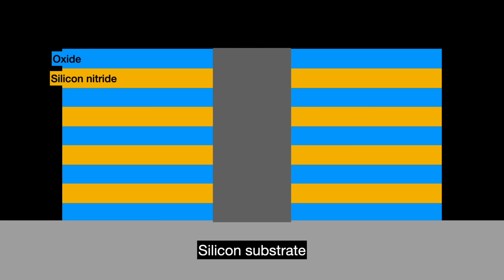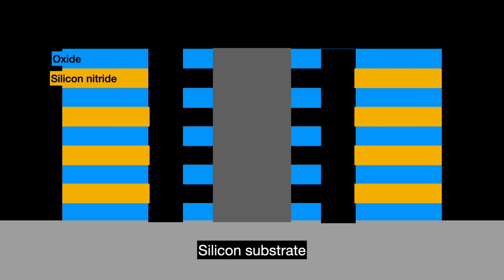Instead of depositing the various charge trap layers, we fill the shaft with polysilicon to produce the channel. If you recall, BICS did this last. The next step will be to create the metal gate surrounding the channel. But if the shaft is already filled, then how are we going to reach the lower levels? This is done by digging trenches on the sides of the layer stack.